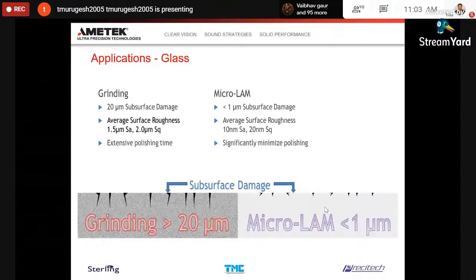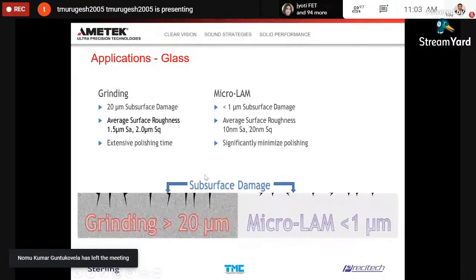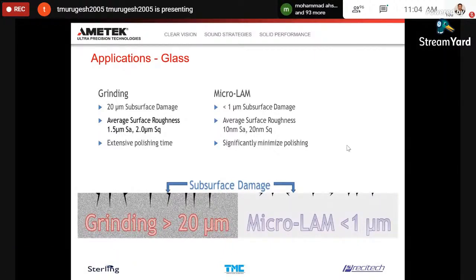For example, sometimes you would also ask, what would be roughly the surface roughness on a glass material? Here Sa is nothing but the whole surface area roughness. We always define it somewhere around 10 nanometers. But when we talk about optics on glass, some people would demand more, sometimes 0.1 nanometers, or sometimes 0.01 nanometers, when we go for optics applications for space. But using diamond turning, you are going to eliminate this, and it significantly reduces the polishing time and the pre-grinding, or I would say, preforming of the glass.